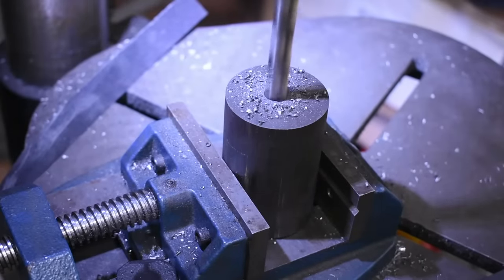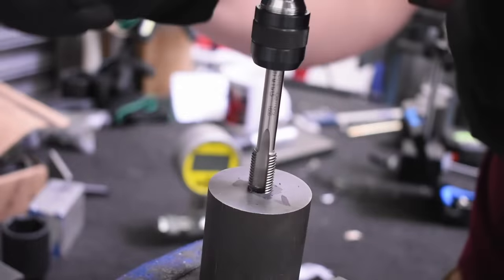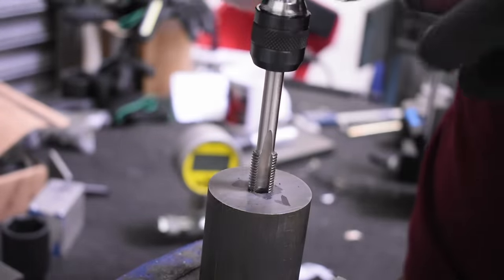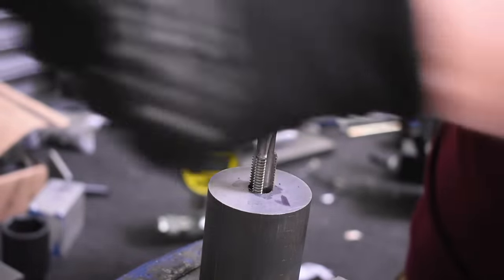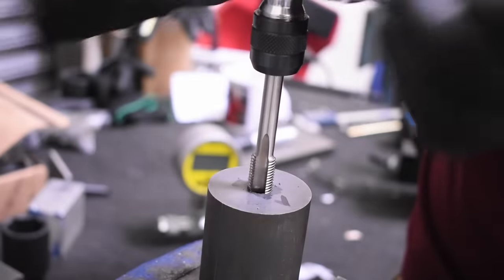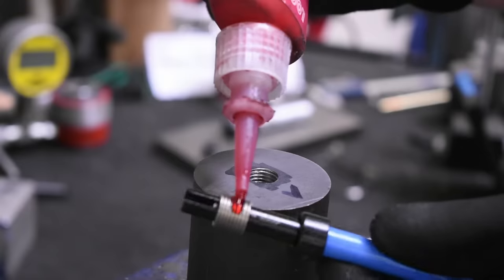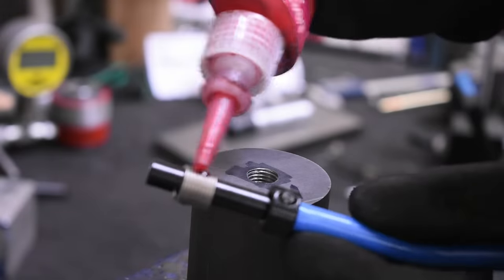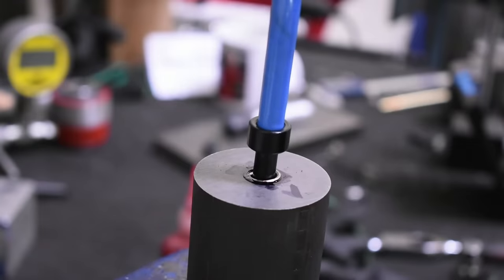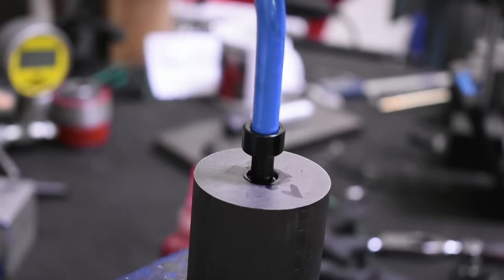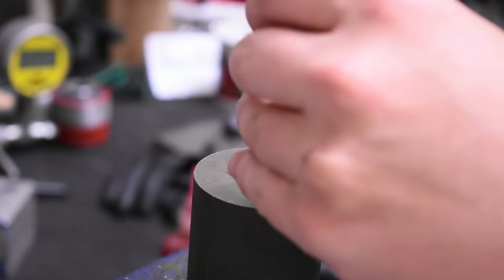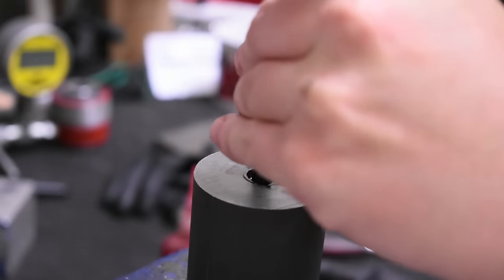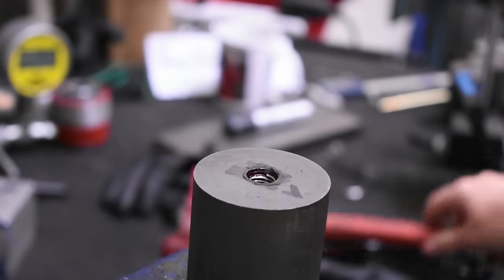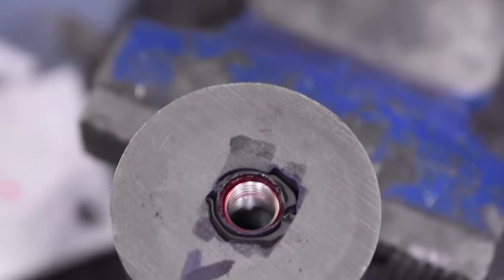Same steps as before: drill out the old threads, use the tap to make new ones. This one felt a little bit smoother on the hard cast iron, but that's subjective, of course. Then use the installer to thread it in. Again, we use red Loctite. Then use the included punch to snap off the tang. You'll want to clean off any excess Loctite and use a blowgun to blow out the tang. A magnet won't work for this 304 stainless.